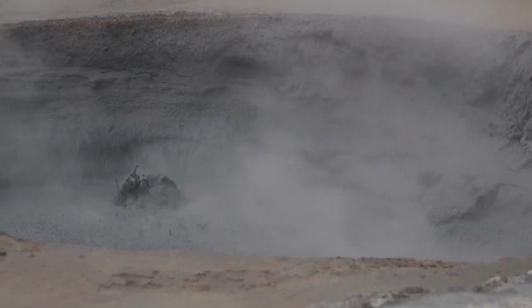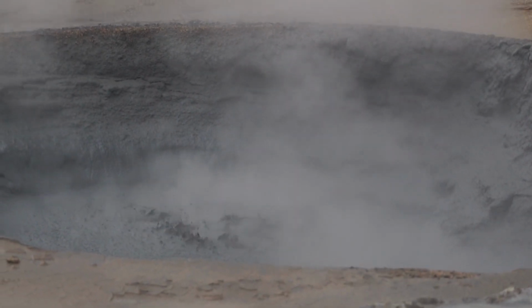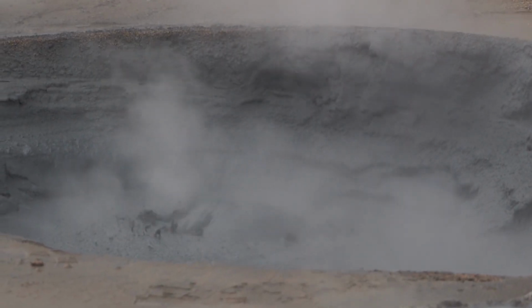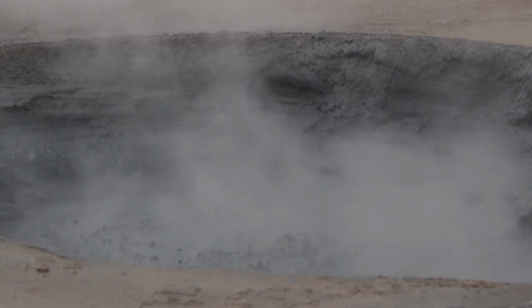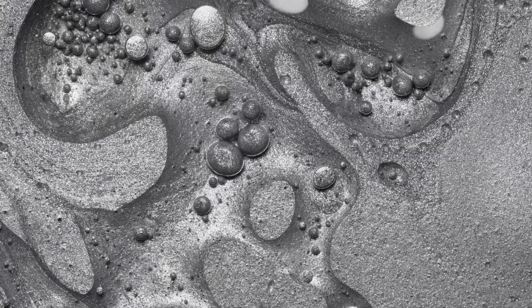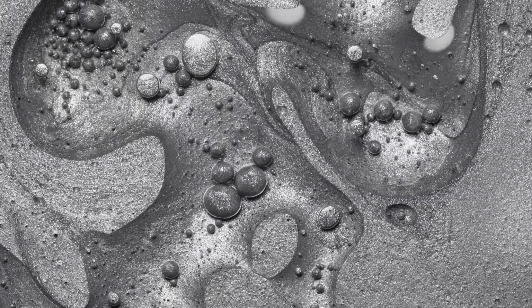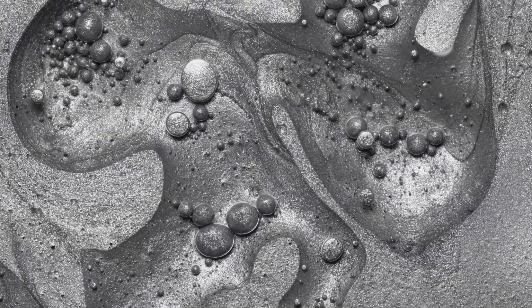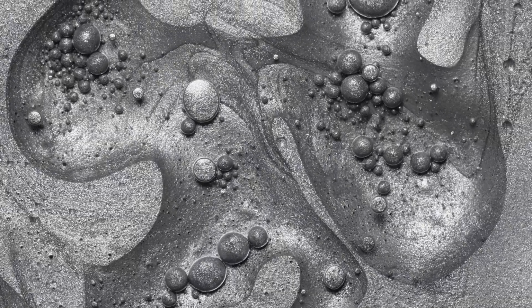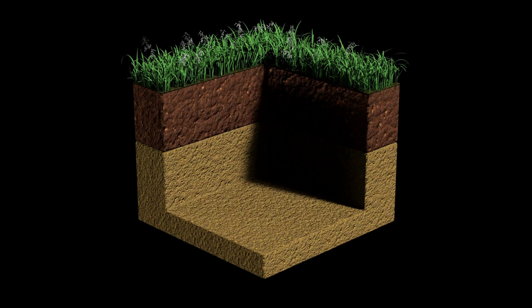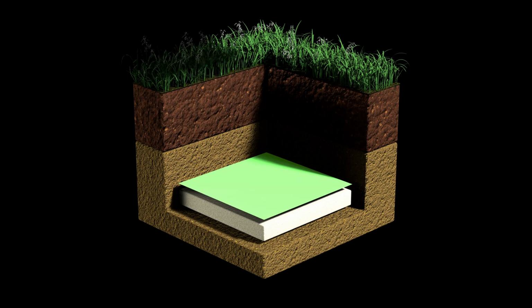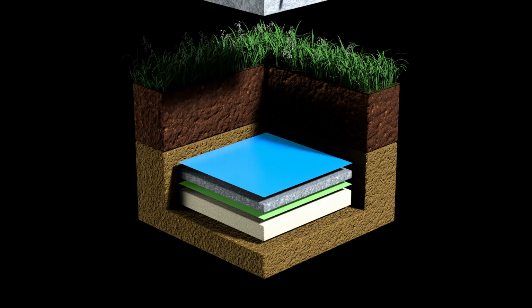The key is not one secret ingredient, but a system. Volcanic ash pozzolana, reactive lime made hot, aggregate that works with the binder, and a structure that doesn't depend on buried steel. The result is a material that can self-heal microcracks and even grow new mineral glue when seawater or rain infiltrates. Let's walk the evidence chain. What the mix was, how the matrix forms, why cracks don't doom it, and where modern design diverged.